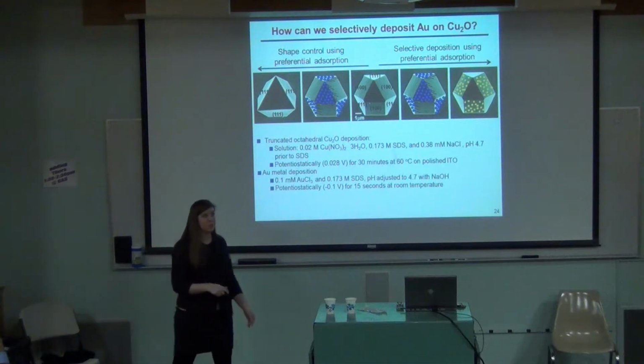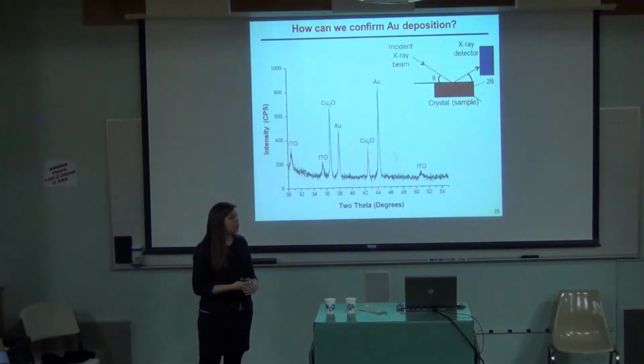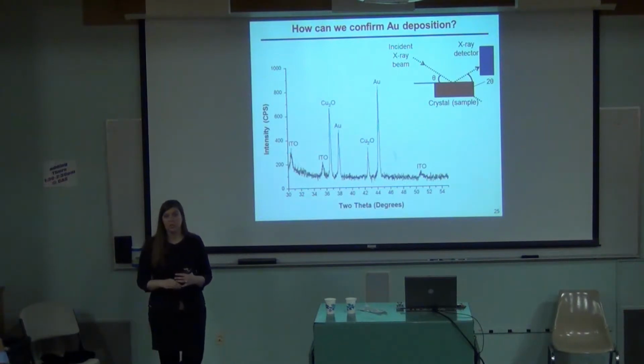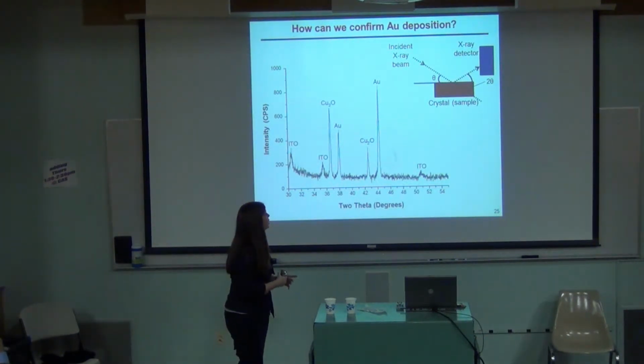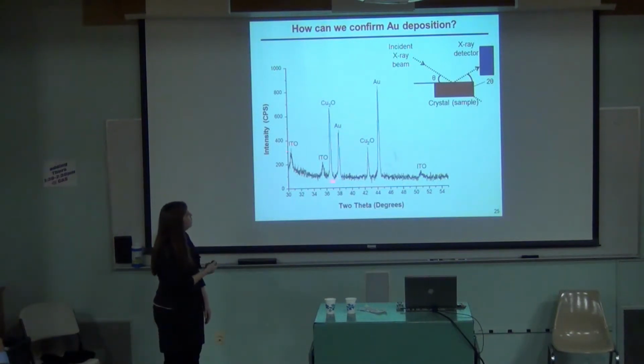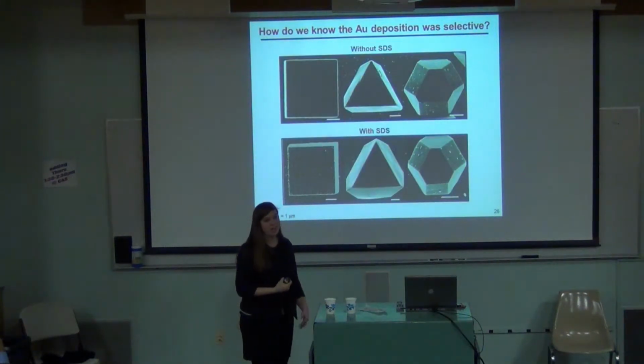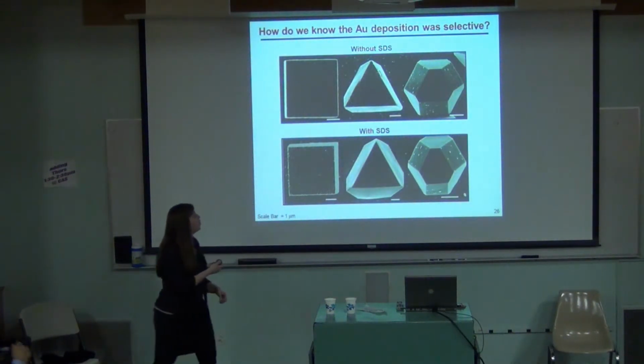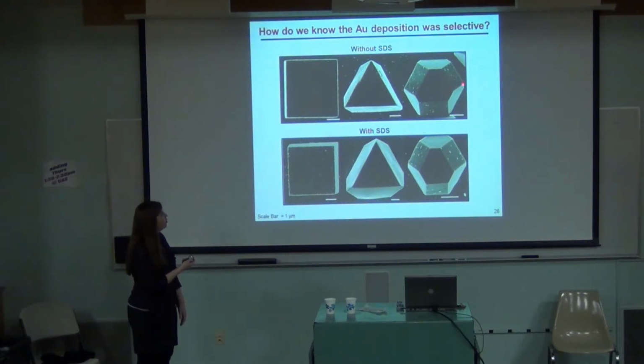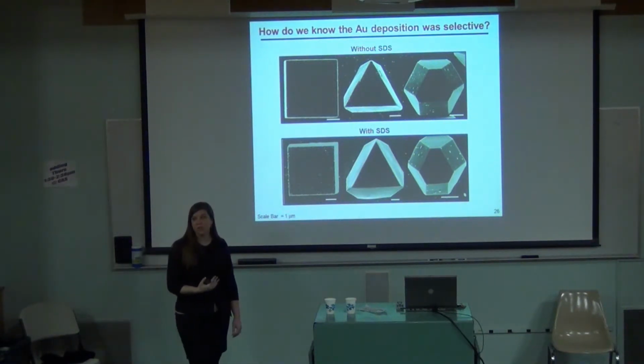So that's what we hypothesized based on our synthesis conditions, and we ended up getting XRD, which is X-ray diffraction, where you can see the crystalline type. So I have indium doped tin oxide, copper oxide, and gold. So we knew we had deposited gold, and then we did SEM to prove that we had deposited selectively. So if you don't have SDS in your system when you're depositing gold, it goes everywhere. And I don't know if you can see the little tiny particles in the back, but this is gold deposited on our copper oxide crystal. When we put SDS, there's no longer gold on any of the 1-1-1 planes. So it did, in fact, do what we thought it would do.